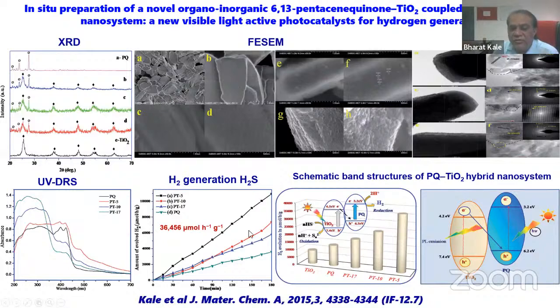36,456 micromole per hour. It's a huge amount of hydrogen, but being organic, the stability we found is much less as compared to inorganic material. So we really work on this again, on how we can enhance the stability with modification of the molecules. So it's very important.